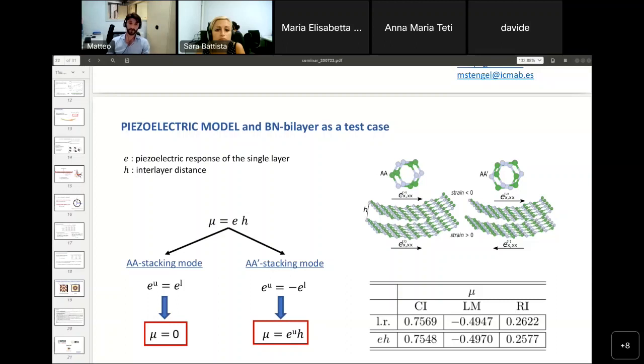Let me clarify that the out-of-plane response can be obtained by applying the open circuit condition, that is, calculating the variation of the electric potential at a fixed electric displacement field. Conversely, for the short circuit, so the in-plane response, it is calculated as the response of the electric displacement field at a fixed potential. In this case, it reduces to the polarization. But actually, you can define it by use of the electric displacement field. Sorry.